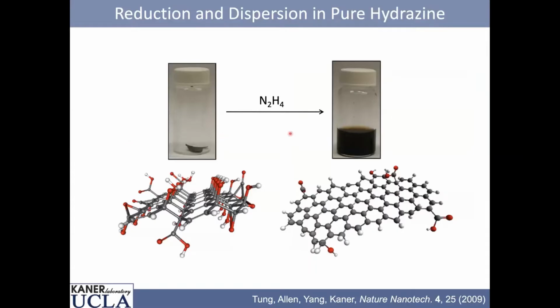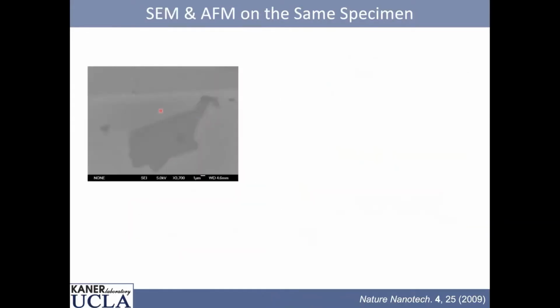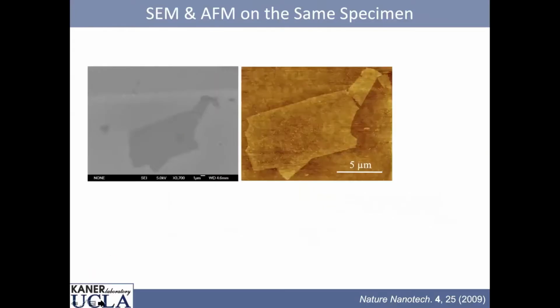We tried to use pure hydrazine because we thought we could make even better graphene instead of aqueous hydrazine. So we took the material, the chemically reduced graphite oxide, and we put it in pure hydrazine, and it makes a dispersion. And now we can get rid of almost all the oxygen moieties. And when we do that, we made at the time the largest pieces of graphene that had ever been made chemically. And if you look at this, this is an SEM picture on the left. Here's an AFM picture on the right. And I think if you stare at these for a moment, you'll say they're the same picture.